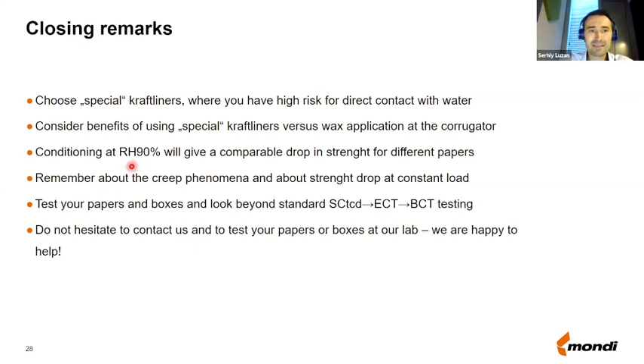So as the test after conditioning at 90% does not give you the full picture and the clear differentiation, if you want to really understand which paper is better for which conditions, then you need to look at the creep performance, subject the paper to a constant load and measure the lifetime under the constant load.